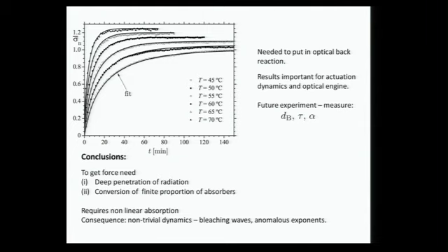So let me conclude. To get force, you need a deep penetration of the radiation. It's no use just illuminating a thin skin on the surface. You need to convert a finite proportion of the absorbers. If you do that, then you have nonlinear absorption. And the consequence of nonlinear absorption is a non-trivial dynamics. And with that, I'll conclude.